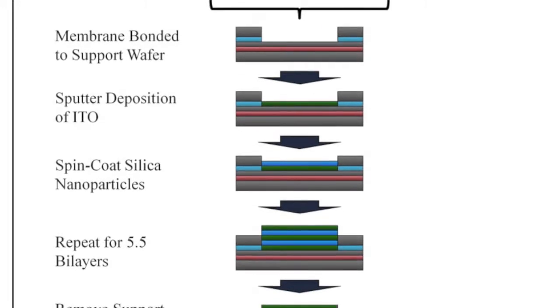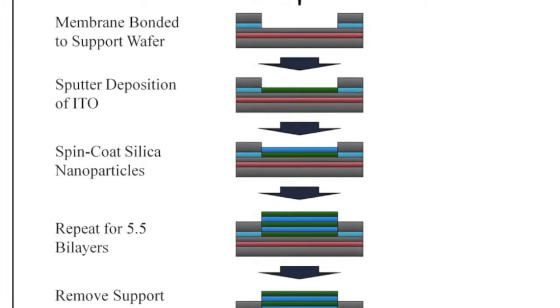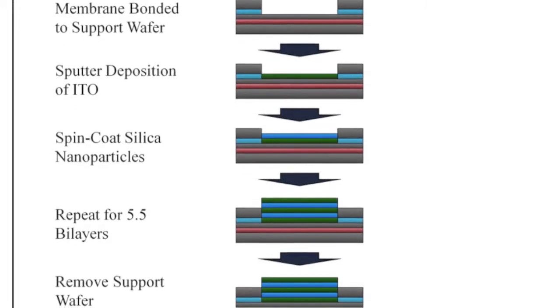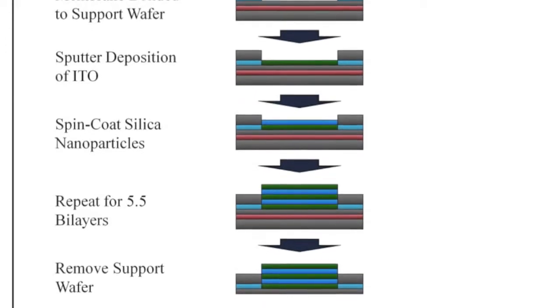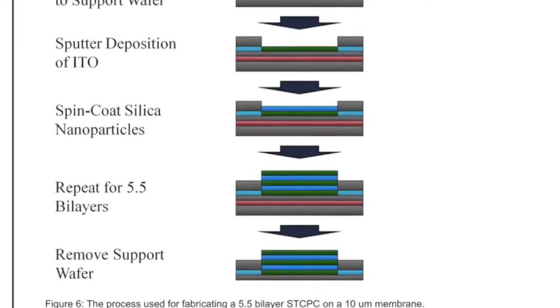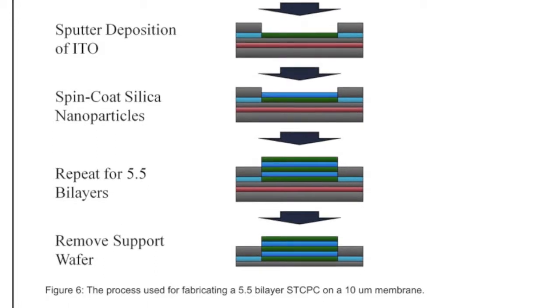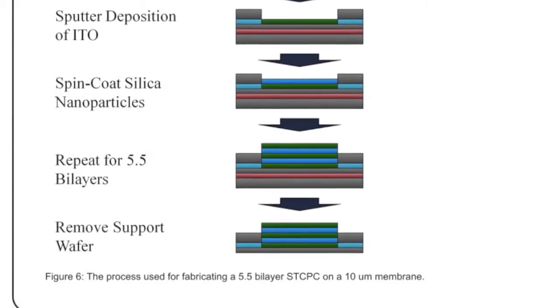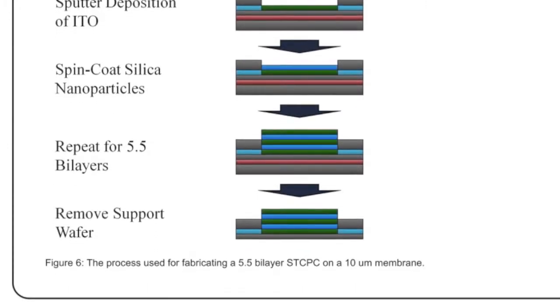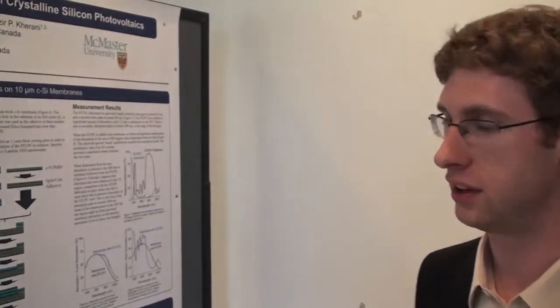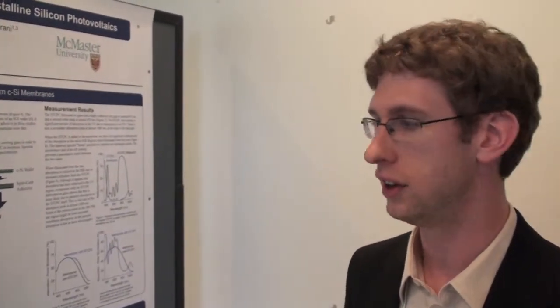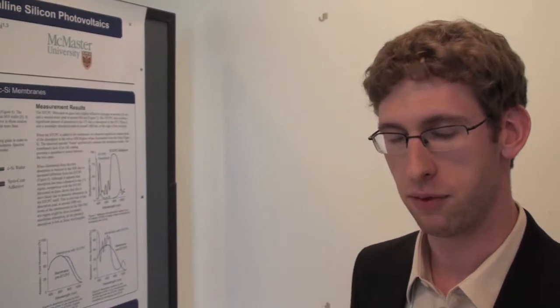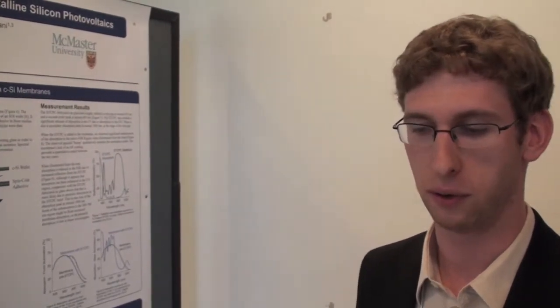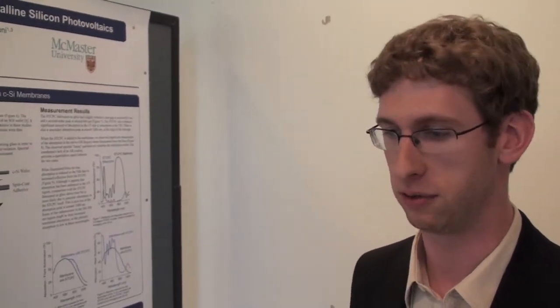From there, we attach that membrane to a handle wafer to offer mechanical support while we go through the rest of the process. We use a combination of sputtering and spin coating in order to deposit the different bilayers, and then did a test to see whether we get the results we wanted. We do see enhancement in the same regions we did in the simulations, and the same for both bifacial cases, when we illuminate from the rear and when we illuminate from the front.